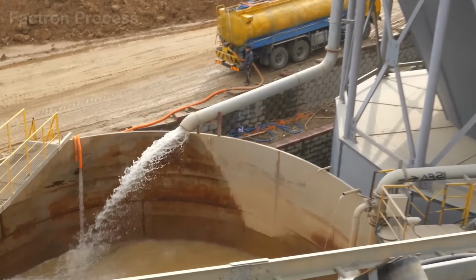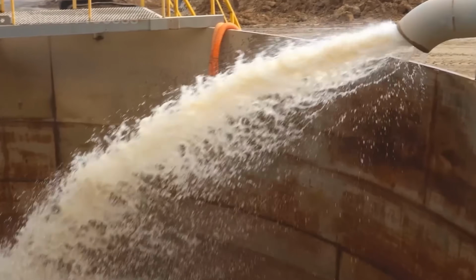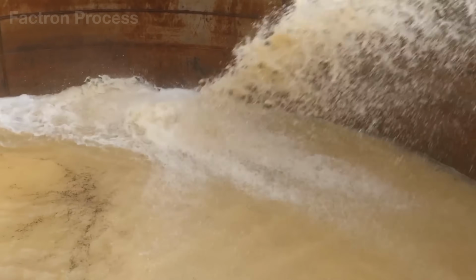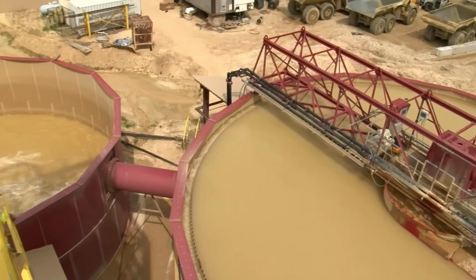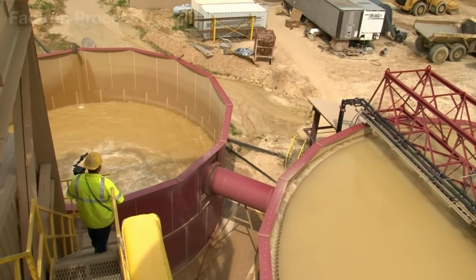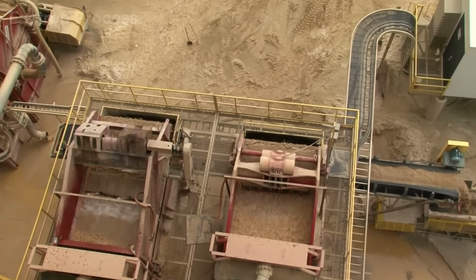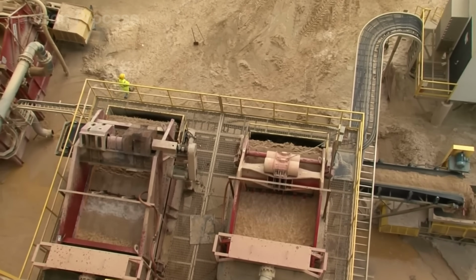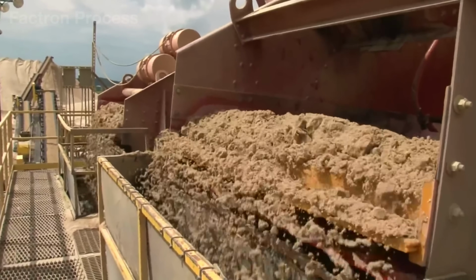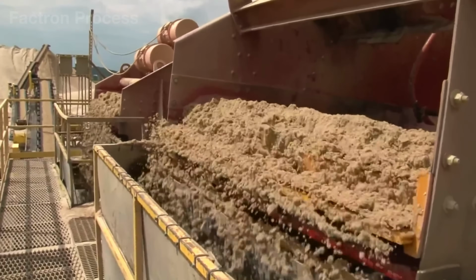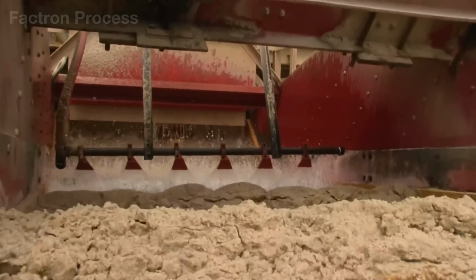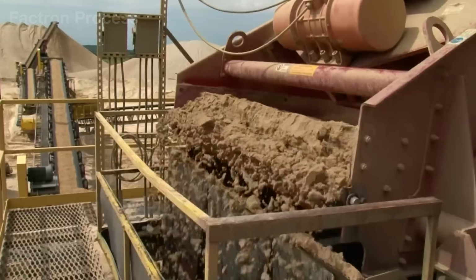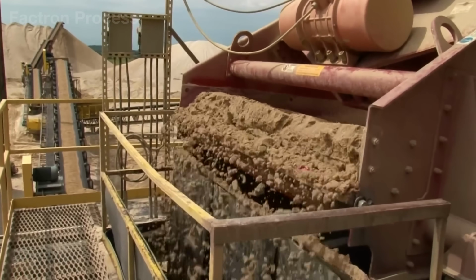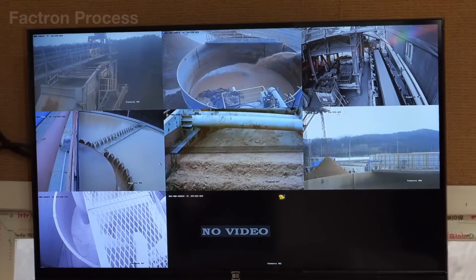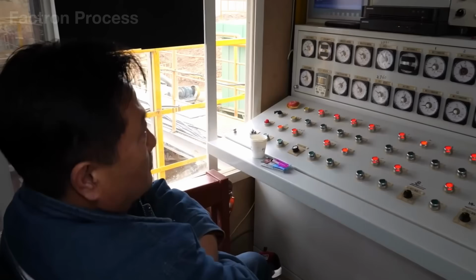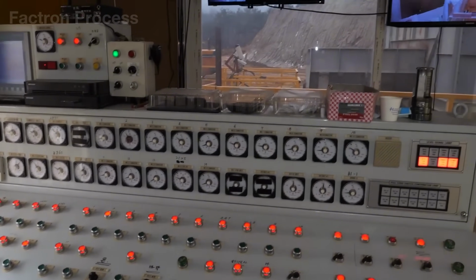Next, gravity separators, magnetic separators, and classification screens remove unwanted minerals, especially iron, the greatest enemy of transparent glass. Even a small amount of this impurity left behind can tint the final product, or reduce the clarity that defines the value of glass. In some modern plants, the entire system can process up to 220 tons of sand per hour. After multiple rounds of washing and separation, what remains is almost pure silica. Only when it reaches the required level of purity is it allowed to enter the furnace.